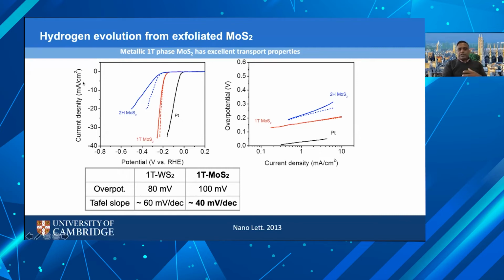So when one measures the catalytic performance of any material, one plots the current density as a function of the applied potential with respect to some reference hydrogen electrode. And so when one reports the catalytic performance of a material that's not platinum, we always compare it to platinum because platinum is the best catalyst for evolving hydrogen. The reason why platinum is the best catalyst is because the hydrogen evolution occurs at no overpotential, and it has a very sharp kinetics, right? So the reaction proceeds very, very efficiently. Of course, platinum is a precious metal, and we'd like to move away from that.